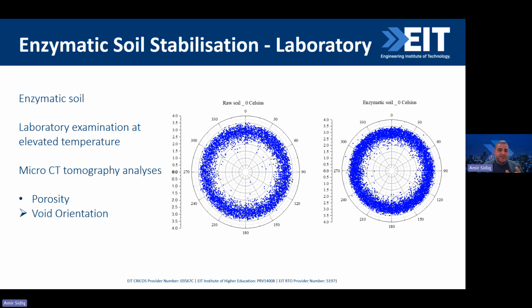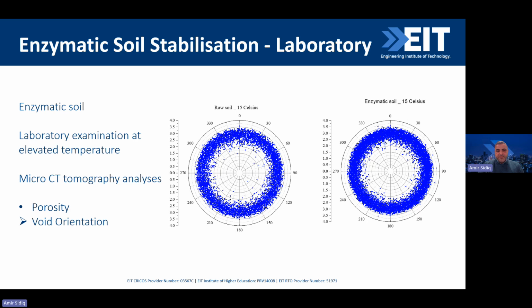So this thicker line represents basically there are some voids going from 2.5 or 2, which is having the shape of the rod to plate-like. Compared to that, the enzymatic is remaining almost over 2.5 to 3.5, which is rod or spherical shape. And that is actually for 0 degrees. Then when we have it for 15 degrees, this temperature is increasing. So you can see the voids within the raw material are actually increasing as well. For the enzymatic, it's again remaining almost constant. And it's evenly distributed, which really means we have different shapes, different angles sitting within the sample.